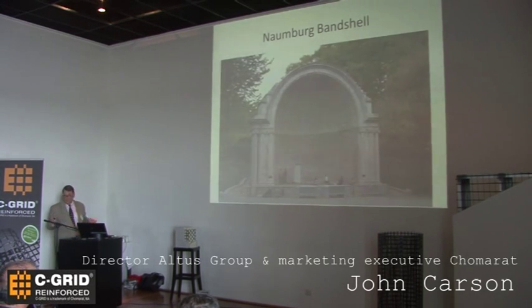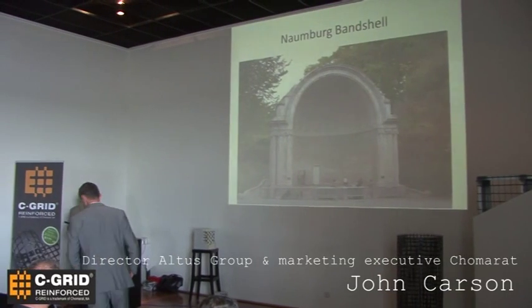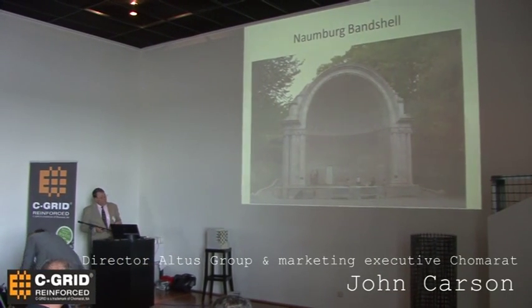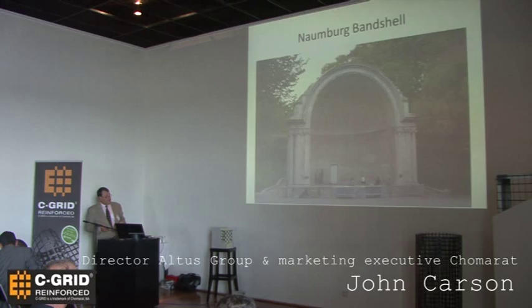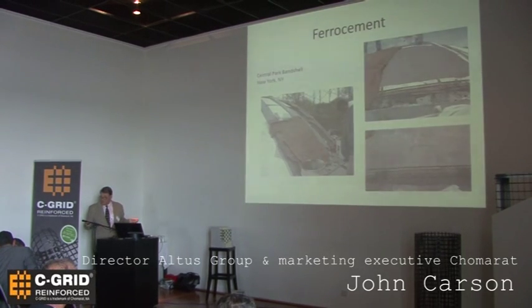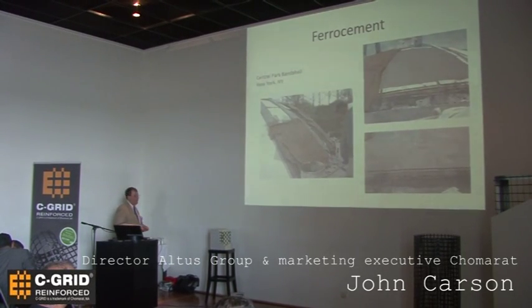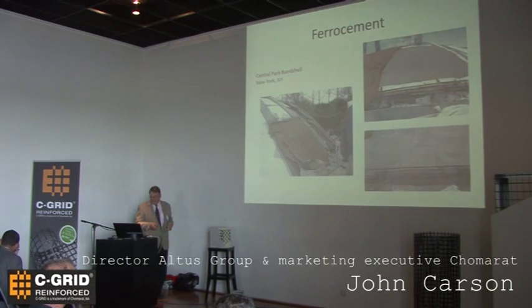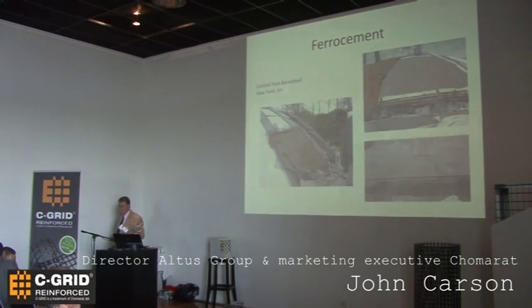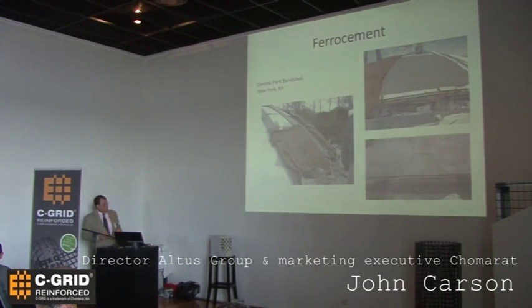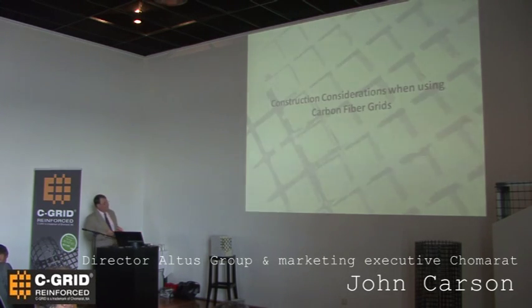And finally, a historical reinforcement project in New York City, which is the Naumburg Bandshell. Here we were using ferro cement as the repair technology to redo a roofing structure for the product. So just to give you some idea, this product used a C-GRID 25 by 25 millimeter grid structure to reinforce it.